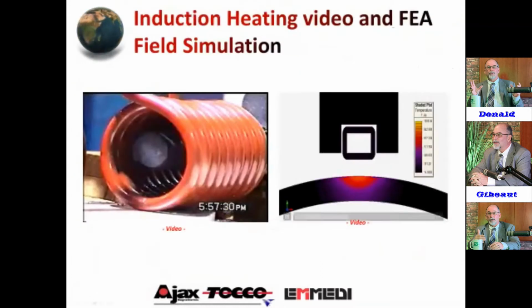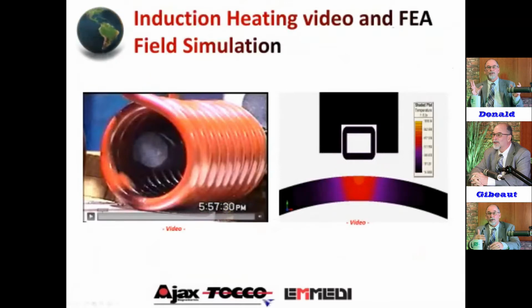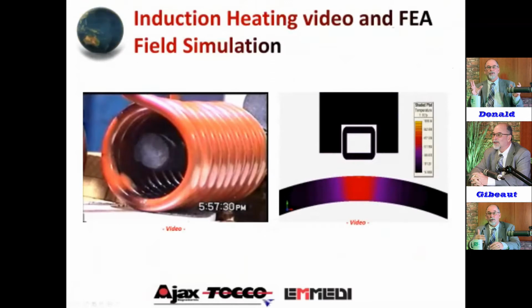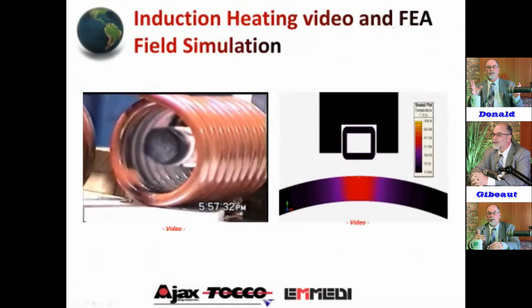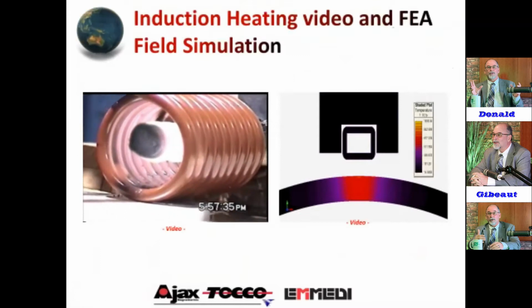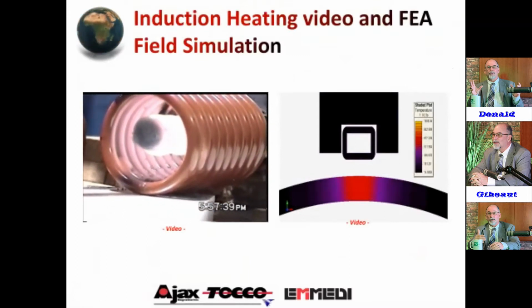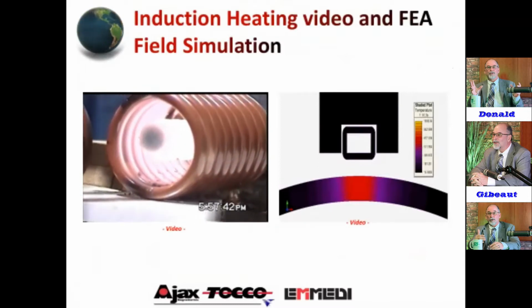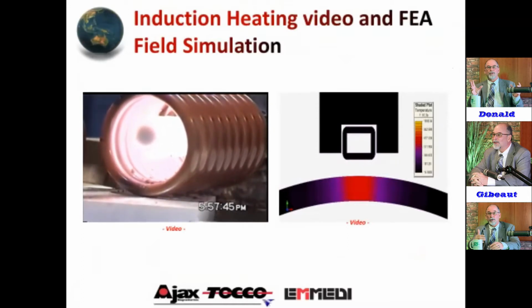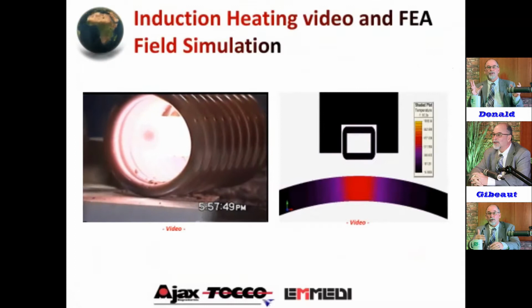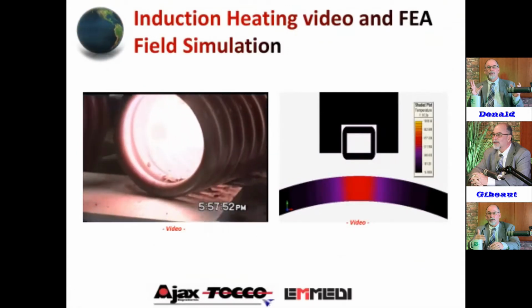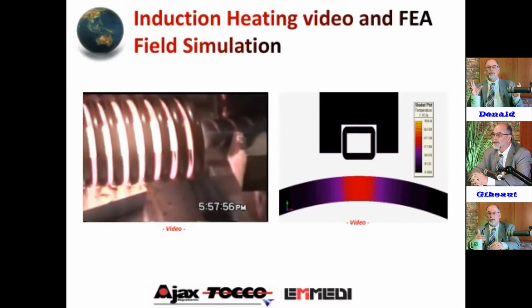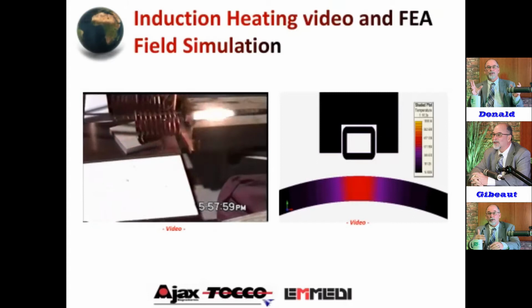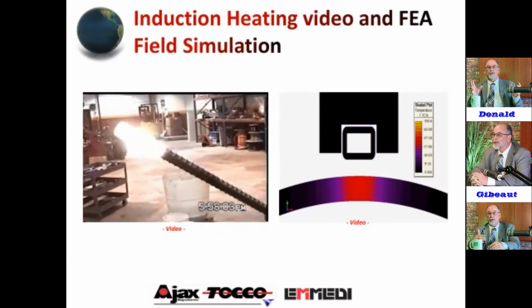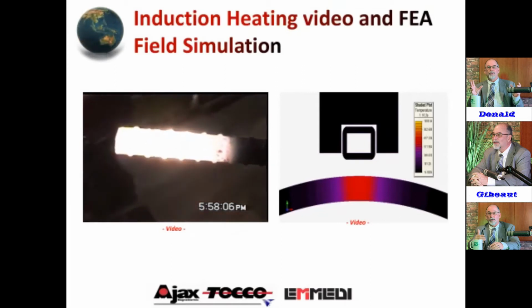Now, if you look to the left, this is a little video that shows heating of a rebar about 1.5 inches. And let me play it here, and you will see that, I think, yeah, I hit it twice. You'll see the induction go out, and you see it go on the surface, that depth of penetration. Then it's conducting, and watch the end of this thing. It's just going to normalize out to the core very quickly. And we're talking like 150 degree delta T is what we target. We're heating here to 2250 degrees. See, right there, normalized out. You can see the rest of the color go together. You saw a little cold on the end. There's cold wall conduction running up the bar, solid bar. But if you look at that, very controlled precision heat on the length, and 150 degree delta T on the core to surface.